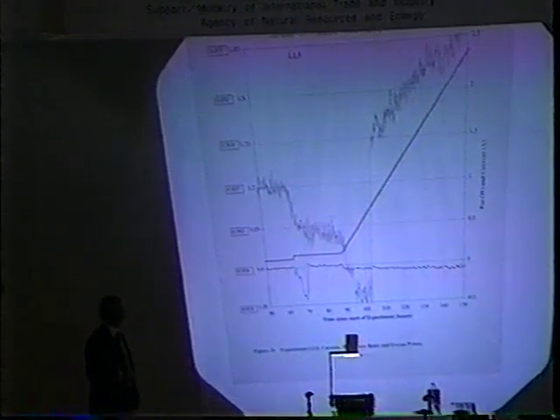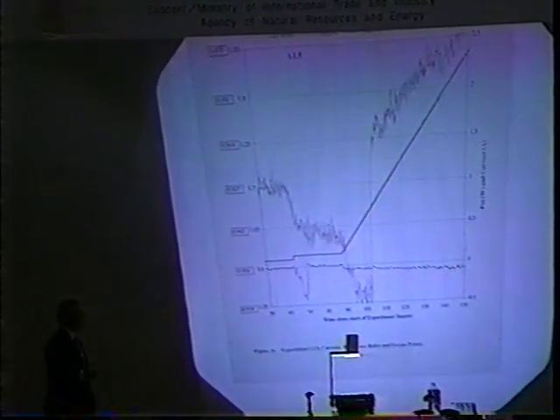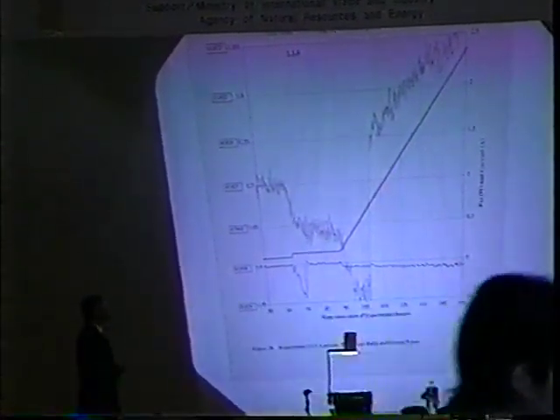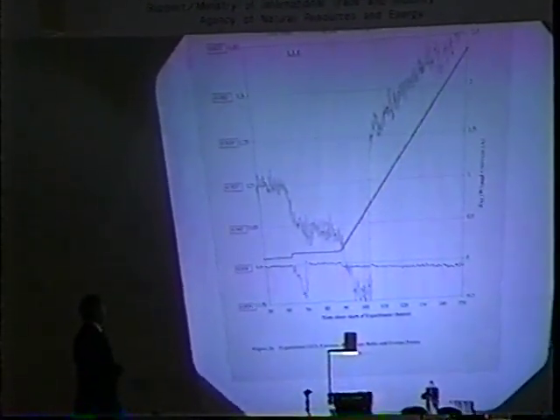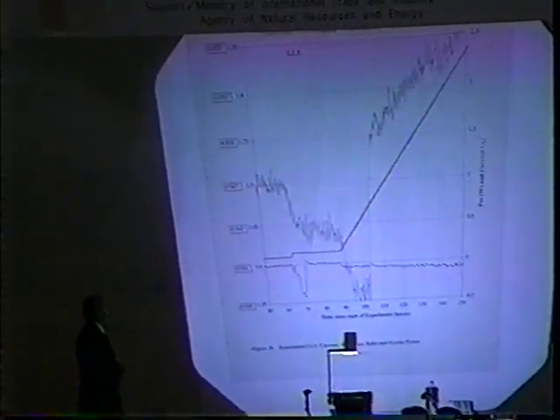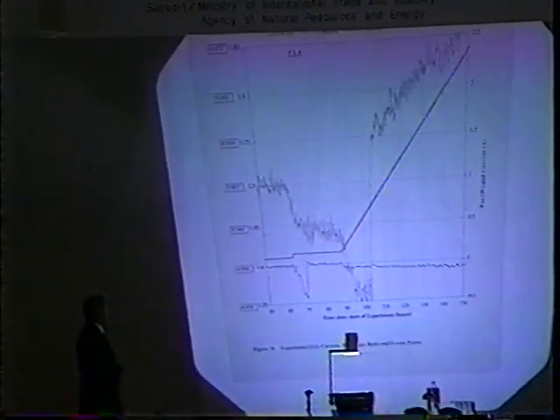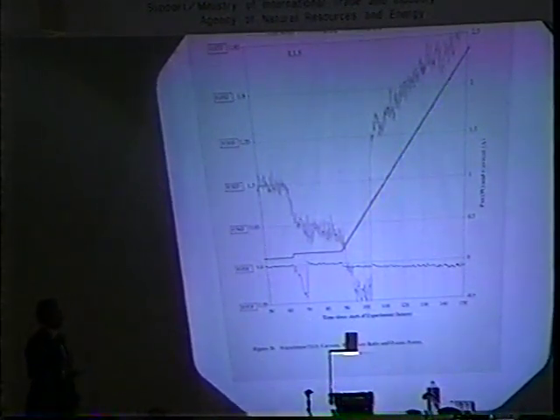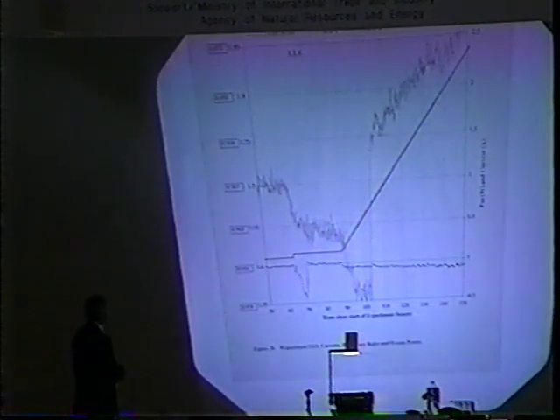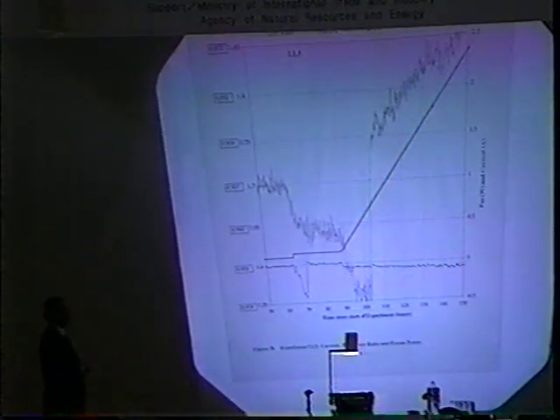This was the point of my poster yesterday. We understand it completely. It can easily be corrected for, but what I've presented here is the raw data. And if we took these to the non-steady state correction, this calorimeter would null at 0 within 20 milliwatts for the entire duration of this experiment, except for that. There is no heat capacity non-steady state correction needed or possible